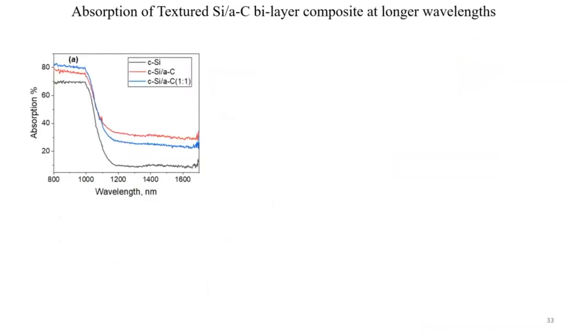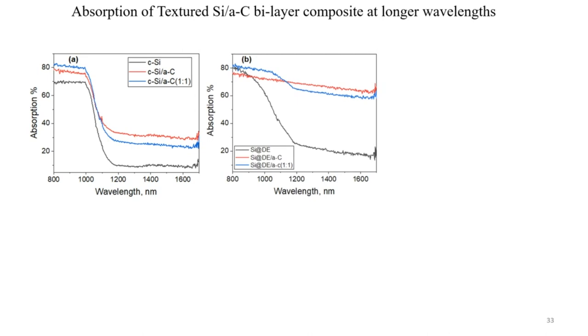But at longer wavelengths, the absorption of silicon drops significantly, and this is also the same for textured or black silicon surfaces, because almost all the light goes through silicon. And so this is where the carbon overcoating proved to improve the absorption properties over a broad range of the electromagnetic spectrum.